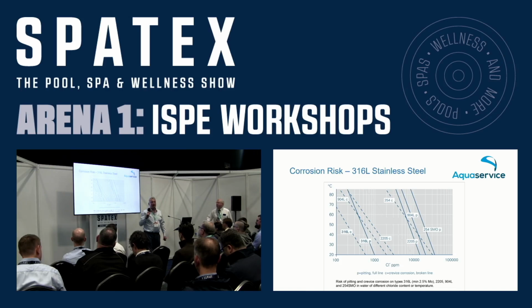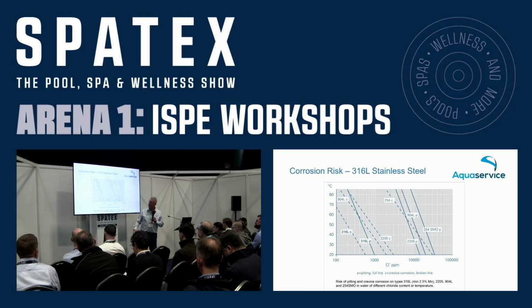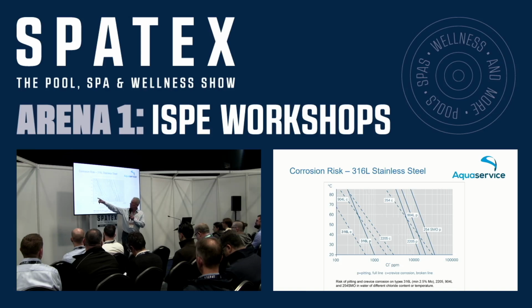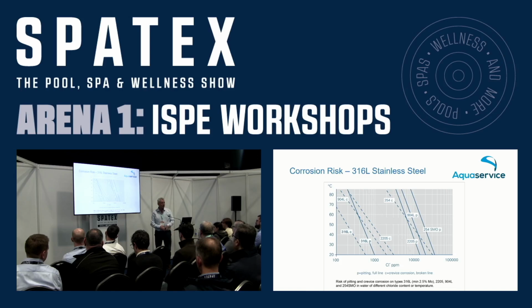So I'll just repeat that. This chart shows on the horizontal axis the concentration of the chloride ion in the water, and on the vertical axis, the water temperature. And if we look at, say, a typical pool condition, around 30 degrees Celsius, we go across this line here and drop down. That indicates that at a concentration of just 400 ppm, or milligrams per litre, there is a significant risk of crevice corrosion occurring.